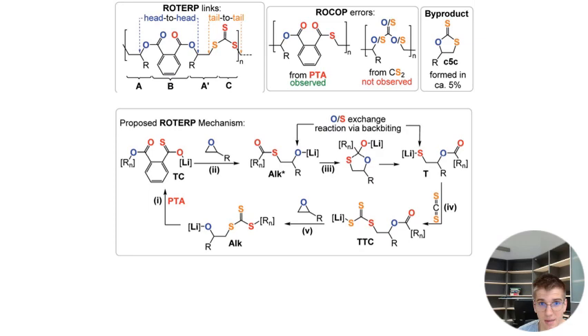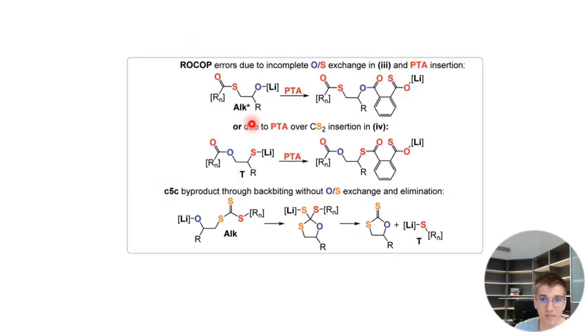So what I thought at the time these errors are originating from are like when the alkoxide next to the thioester then does not do this rearrangement and inserts the cyclic thioanhydride. Yeah, and by that you have some thioester errors in the sequence. Alternatively, when the thiolate after the rearrangement does not insert CS2 to form the trithiocarbonate, it inserts PTA to form thioester bonds, right? Because you can now dial back and look at the carbon spectrum again, and there you see there were some thioesters in there. Yeah, so I had to formulate some hypothesis where these originate from, so to say.